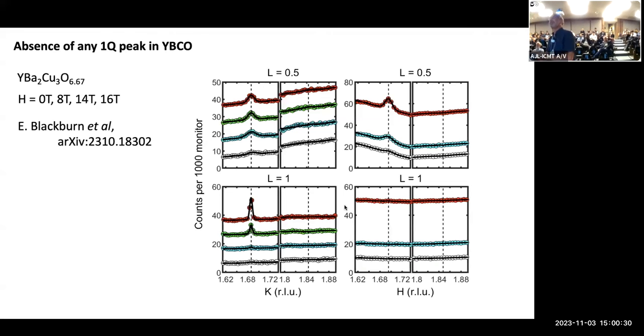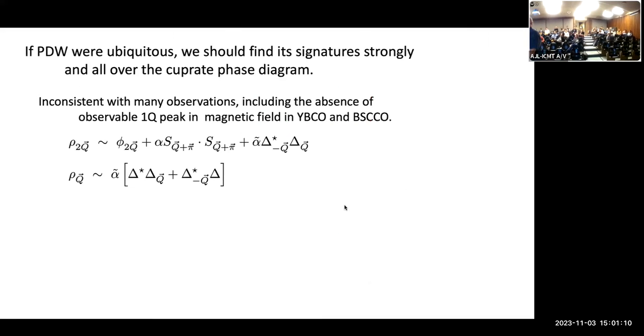And here is the attempt to see a 1Q peak in YBCO in a range of magnetic fields to tune the relative strength of the pair density wave and uniform superconductivity. Here you see, as the magnetic field is turned up, the charge density wave strength at 2Q, in this case here around 0.68, turns up. And as you see, there's absolutely nothing at 1Q. So this proves that there isn't pair density wave here. Well, proves, I would like to make sure that we can see it where we want to see it.